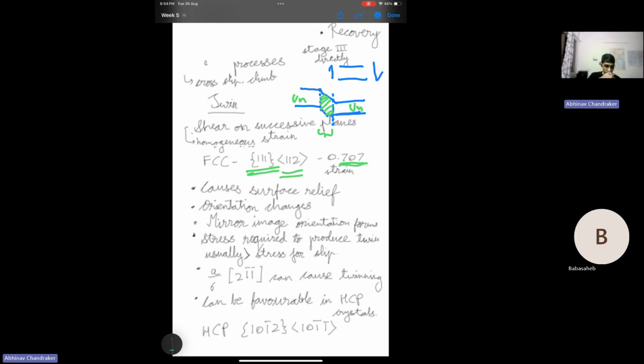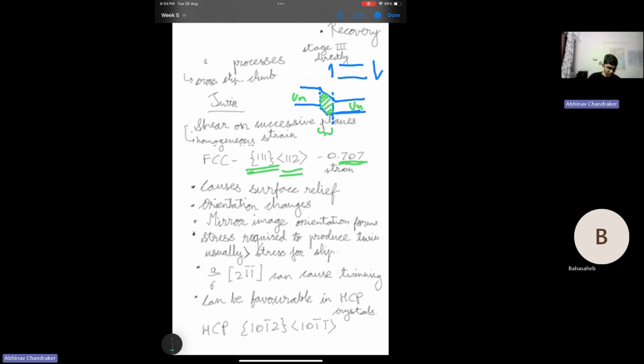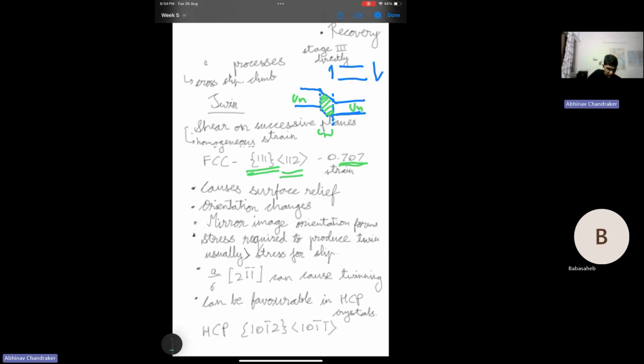Atoms move along the 112 direction, but on the 111 plane. And this also causes surface relief, just like slip steps. There is an orientation change which occurs here, which does not occur in case of slipping. So in case of slipping, it's just movement of extra half plane which is taking place. But here the orientation is changing, and the orientation becomes a mirror of the matrix orientation.